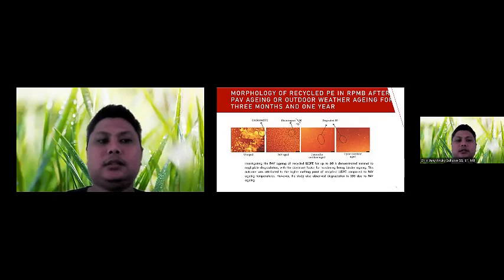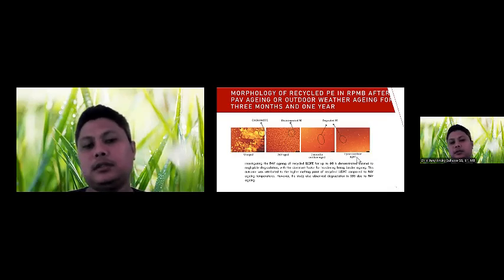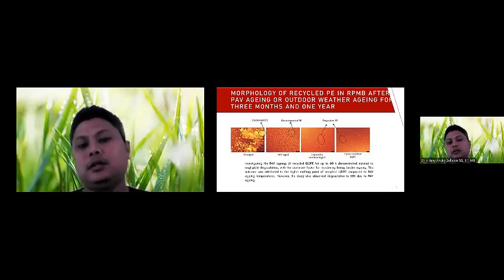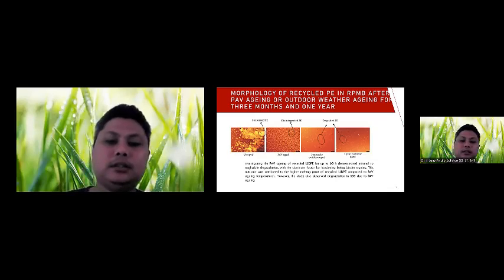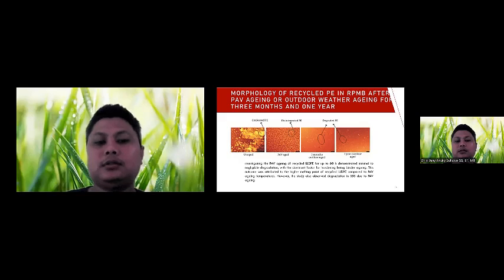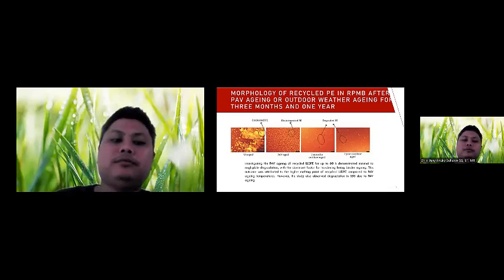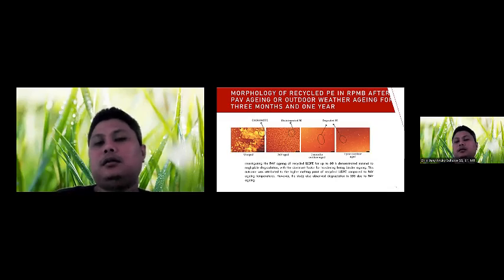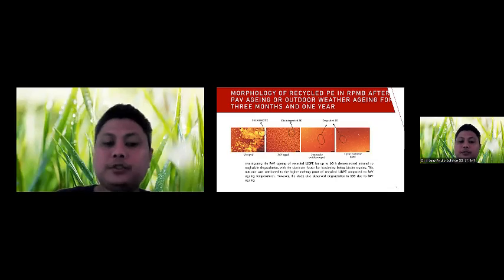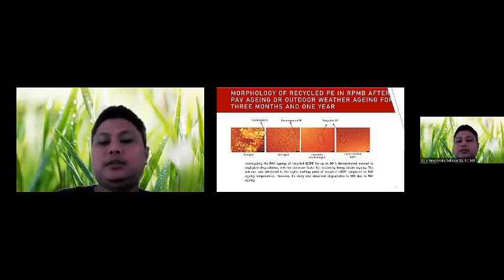This is the morphology of recycled PE after aging and outdoor exposure, and of PE aged for 3 months and one year outdoors. This demonstrates negligible degradation, and the dominant factor for the hardening is the bitumen aging. The outcome for this morphology is that the higher melting point of recycled PE combats the aging temperature. This research is about the observed degradations in SBS and PE aging.